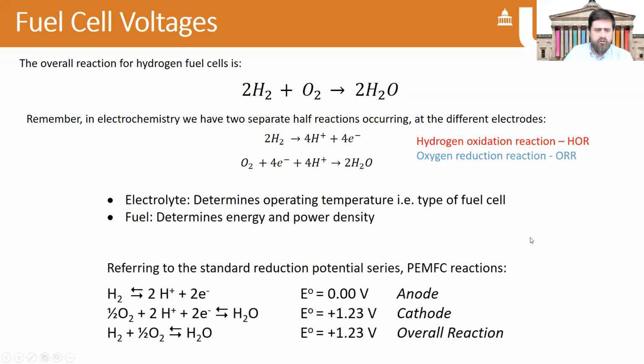There's also an associated voltage with this. All electrochemical half reactions have a voltage, and this is a somewhat arbitrary voltage that's been defined, actually quite usefully, by the hydrogen oxidation reaction. So this is defined as 0, and it happens that the oxygen reduction reaction is at about 1.2 volts positive of that. Okay, so if we combine those two numbers, we can get an overall cell voltage. That means the starting cell voltage of a fuel cell is around 1.2 volts. Okay. If we used a different fuel, like methanol, for example, this wouldn't be the same voltage, and therefore our cell voltage would be different and lower in the case of methanol.